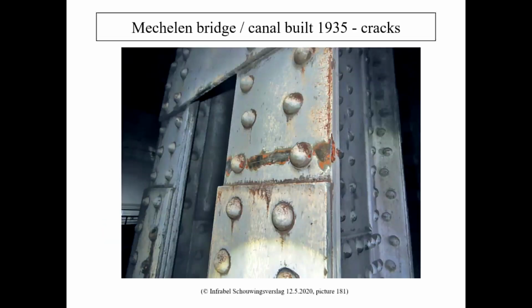But more problematic, more worrying, some very fine cracks were noticed in the vertical posts of both main Vierendeel girders at a limited number of locations, 7, 8 places on both girders. These cracks are very hard to see, often invisible under a layer of paint. They may have escaped previous inspections. But this was worrying enough to limit the traffic on the bridge. Say only 1 track and 40 kilometers maximum per hour. And also